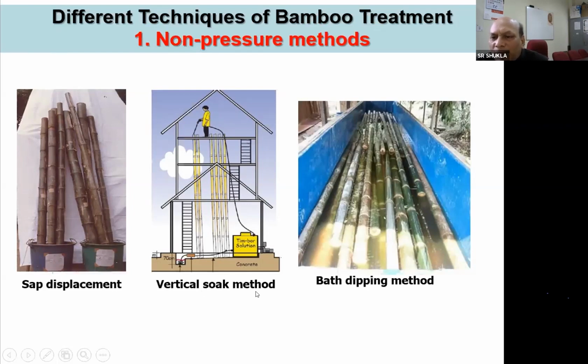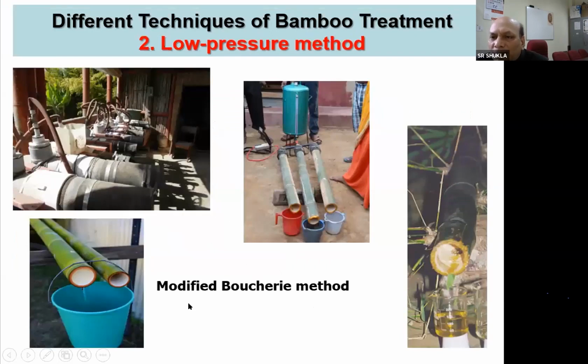quantity can be limited. Second is the vertical soaking method, and third is the bath dipping method, where we take the bath and just dip the bamboo for some time, and then bamboo can be treated. This is a low pressure method, like Boucherie, the modified Boucherie method, where a small chamber is there where we fill the chemical, and a small amount of pressure is applied, and bamboos are attached with the nozzles, and then the chemical can flow through the bamboo, and it will start dripping on the other side of the bamboo. So this is also a very cheap method, not very expensive. It can be used in field conditions also.